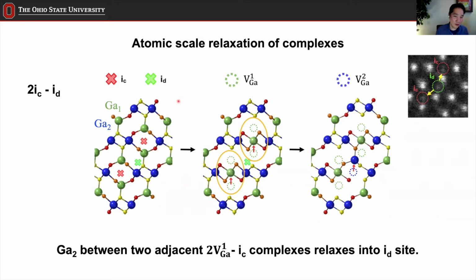So what we found is happening is secondary relaxation, essentially, when there are two neighboring interstitial-divacancy complexes. So this complex right here is something that I already explained, right? So the extra jumping here creates another vacancy. So you have one complex here. What if another complex forms right next to it? Okay, so if that happens, then you actually have an empty space in between, which is pretty large. Intuitively, you think this is a little unnatural. In fact, what happens is we figured this atom jumps into that site, which we named as the ID site. Okay, so that atom jumps into the ID site, so it actually bridges this structure and that structure. Okay, so that's what's formed here.